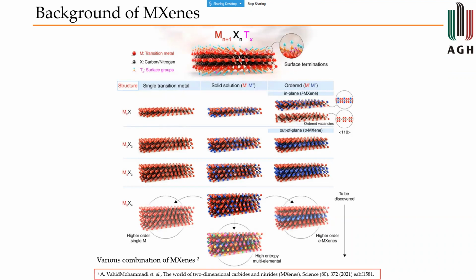So in MXenes, the M represents transition metals, and the X represents the carbides and nitrides, which are formed. What you see here is a typical single layer titanium carbide MXene, where you'll have 3 layers of titanium and 2 layers of carbide. And it also has surface terminations. The surface terminations are basically oxides, fluorides, and hydroxides, which give it the property of hydrophilicity to mix well with water, with polymer, etc. So the focus today would be on just one type of MXene, that is titanium carbide, Ti3C2. But there's a host of other options that have been developed.